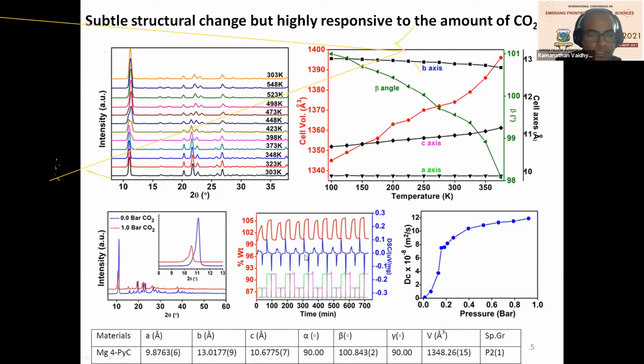So that is what I'm seeing. But I'm also seeing that the material is able to show beautiful uptake of CO2, which can easily be removed by a sweep of nitrogen. And again, you can uptake CO2 and you can again sweep it down with nitrogen. So I can do multiple cycles of CO2 adsorption and desorption on this material, but only above the gating pressure, not below that. Okay, that is what I'm showing you here.